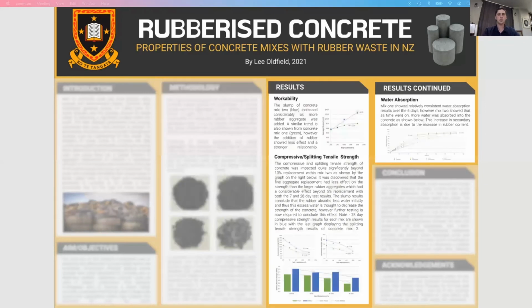As shown here, the slump of concrete mix 2 increased considerably, meaning it was a lot more workable with more rubber, while concrete mix 1 showed a similar effect, but less significant due to the larger rubber particles.